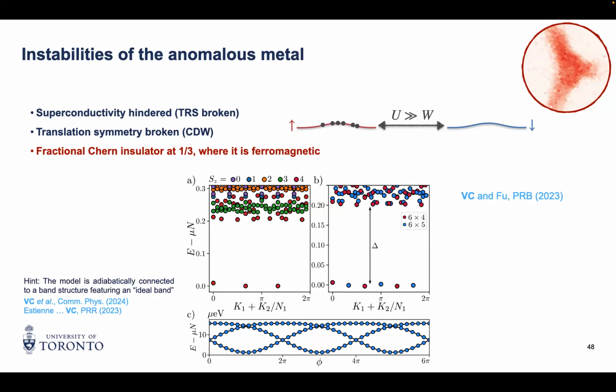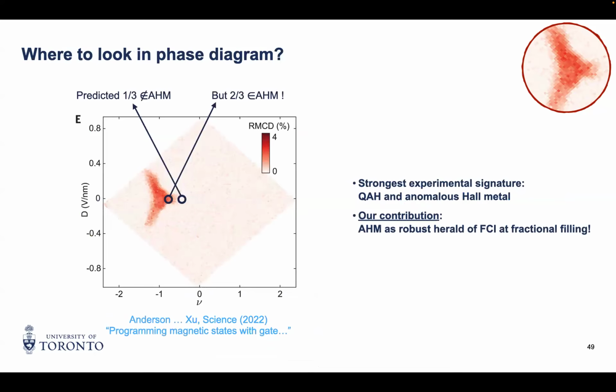If they are independent of the field, then probably you have a state without any Hall conductivity, so it's a charge density wave. If you see that things move as a function of magnetic field, then most probably you have a response with a non-zero Hall conductivity, and you are more likely in the fractional Chern insulator scenario.